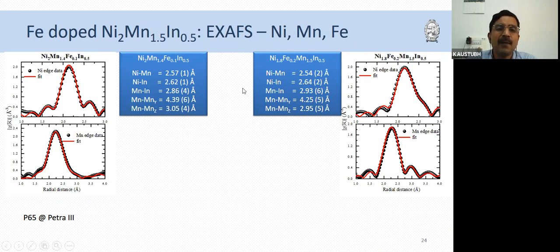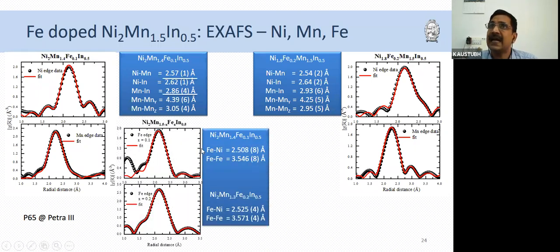This alloy was antiferromagnetic, so this Mn-Mn distance, which is a characteristic ferromagnetic distance, was much higher, whereas in this case it was at 4.2 angstrom, which is as expected. Then we looked at EXAFS at the iron K edge. All these experiments were done at the PETRA P65 beamline, and iron is supposed to replace manganese. So if it's supposed to replace manganese, then you should see a manganese-indium or iron-indium bond distance at about 2.86 angstrom. There was no iron-indium bond distance. We could not fit that.